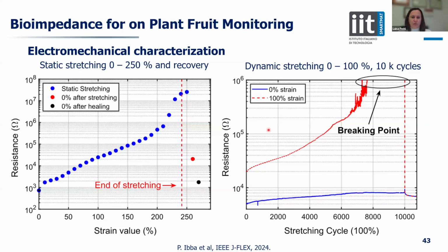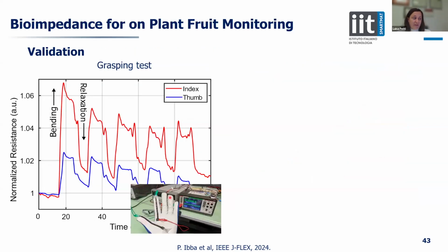Of course, we did lots of electromechanical characterization from static stretching to dynamic, because the glove clearly sees a lot of stress when used. We did grasping tests. Here you see the printed electrodes on the glove. The connection is still very rudimental, but the glove is able to detect bioresistance changes.